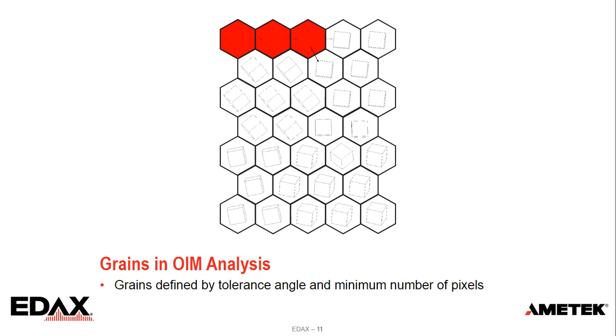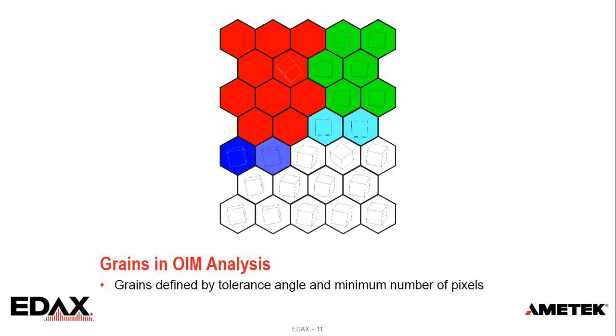And if we repeat the process, it checks and groups things to determine the boundary of the grain. And once it's found, it then colors everything here. And then we go to the next spots and we repeat the process, and we start to fill them in to determine where the grains are. And you can see in this particular example, there's one grain that has 1 pixel, there's one grain that has 2 pixels. We can do some filtering by the minimum number of pixels. And that's important because how this falls into place depends on your microstructure, but also on your sampling size. As you go to smaller and smaller step sizes, you're able to resolve finer and finer grains. And so being able to adjust that, if you go to coarser step sizes, may require a different threshold.